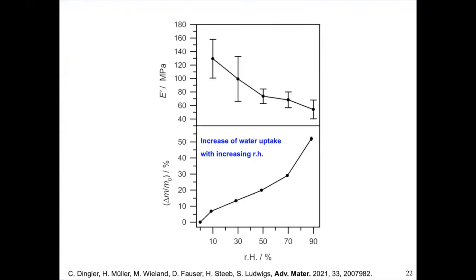So these are the results. Look at the bottom graph first. This is again the picture I've shown before. That's the increase of water uptake with increasing relative humidity. And concomitantly, you find here the storage modulus as function of the relative humidity. And what we see is that this decreases with increasing relative humidity by a factor of 2.4 between the dry and the wet state. So this is definitely a function of the relative humidity.